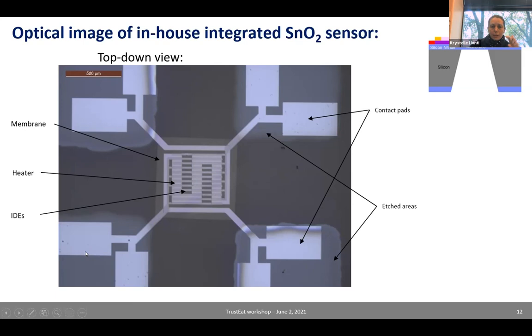Now, one little bump along the road is that when we calibrated the temperature, the maximum temperature we could reach under the maximum voltage we can apply, we realized we could only reach 100 to 200 degrees Celsius when our target was really 400 degrees Celsius, because that's typically where we get the maximum sensitivity for a MOX. But it was not such a big deal in the end, because even at slightly lower temperature, you can still obtain a response for a given sensor. So we moved forward with our initial fully fabricated and integrated sensors.